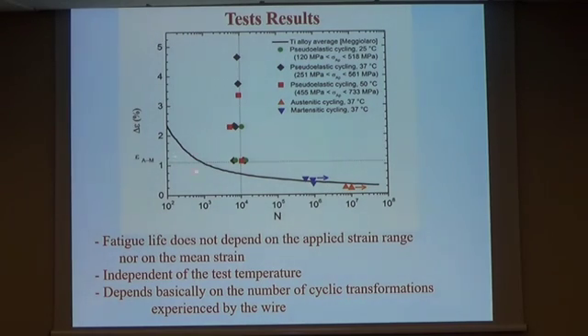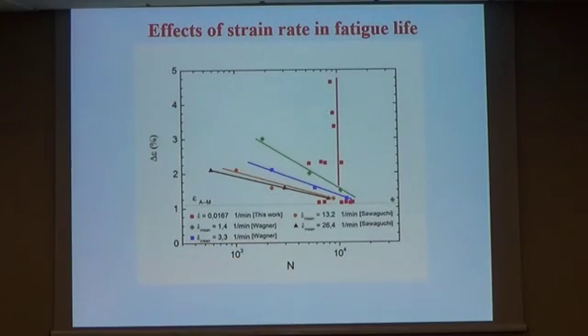But the important thing here is that for superelastic cycling, we have a fatigue life that does not depend on the applied strain range nor on the mean strain. It seems to be independent of the test temperature, at least in this range. So it seems to depend mainly on the number of transformations experienced by the wire in this region. In all cases, the fracture took place in the effective length of the wire with functional fatigue.